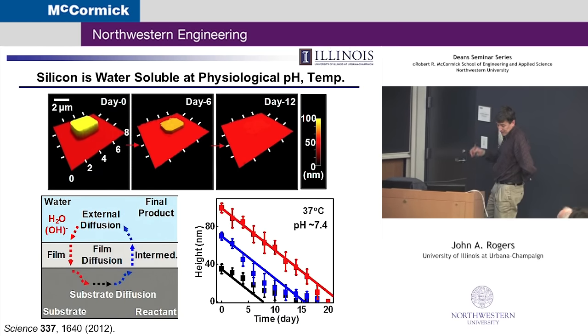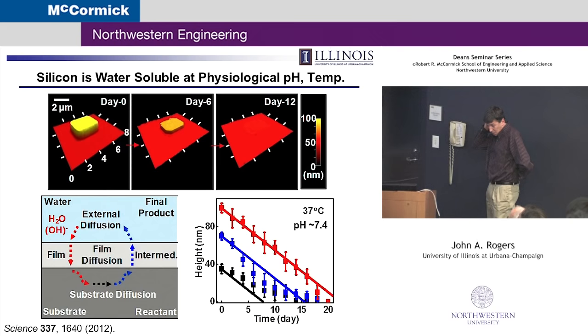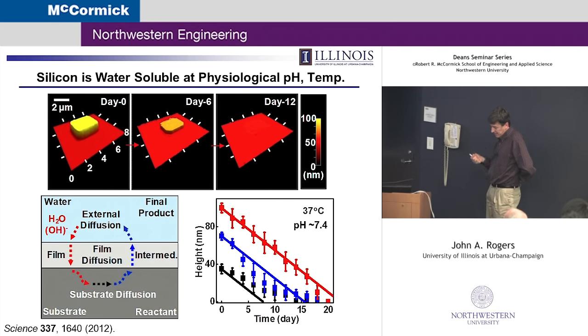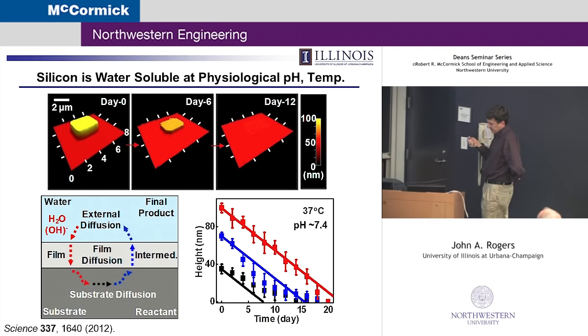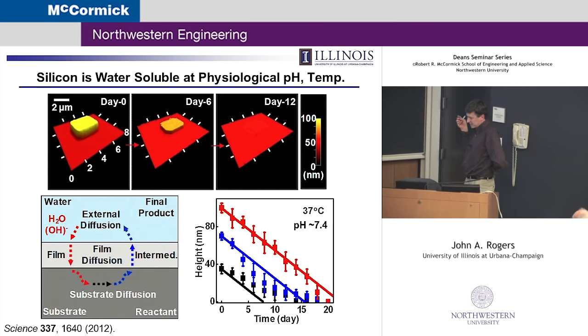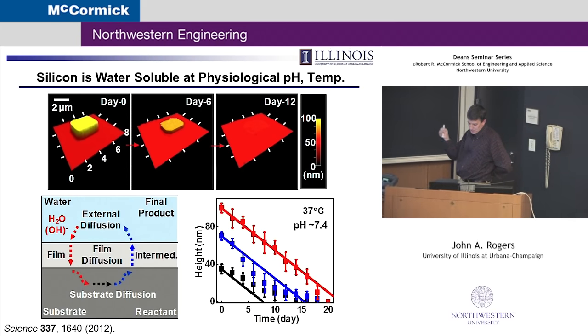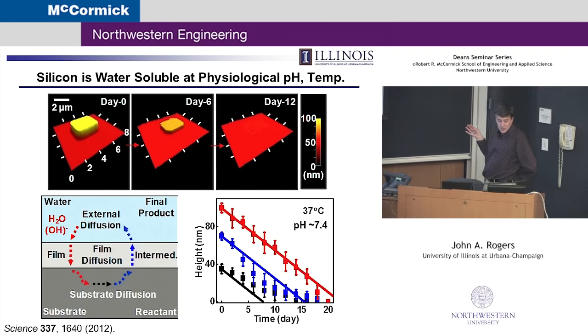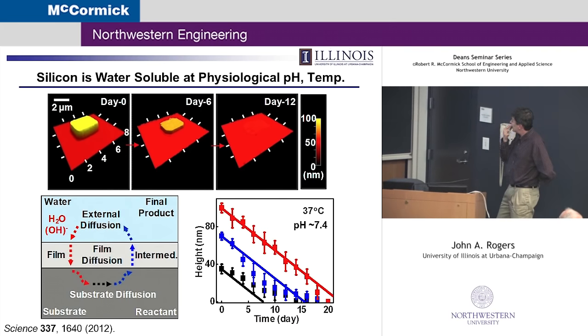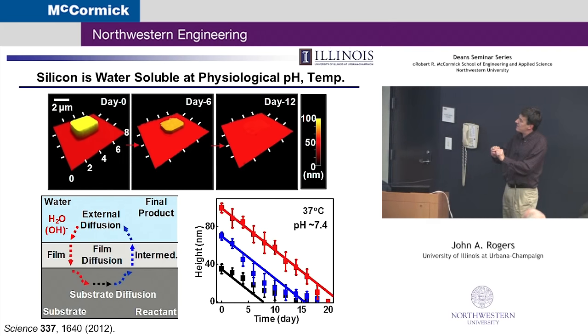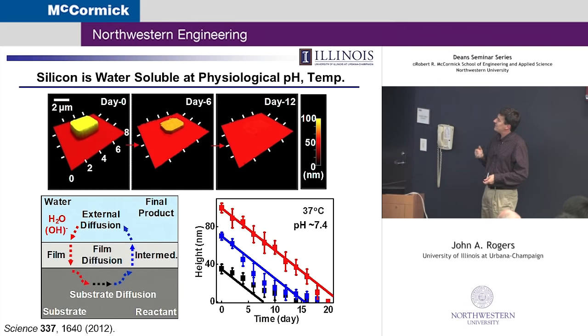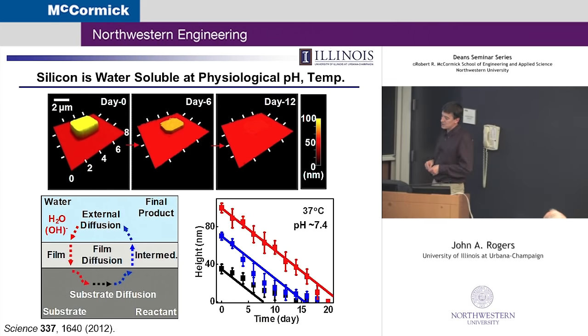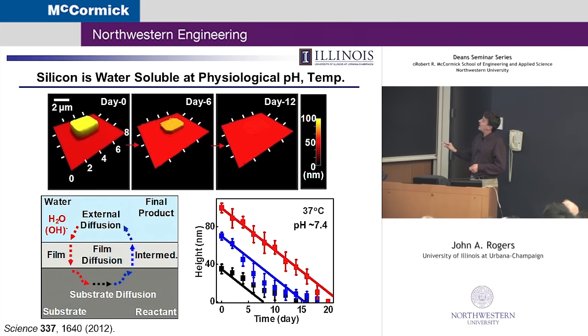So how do you do it? We grappled with this for a while before stumbling on the solution. You think about material selection for electronics, and you add the additional design constraint that it's water soluble, but you might think, there's no way to do that. But it turns out that silicon itself, in these very thin forms, dissolves at physiological pH and temperature values. Because they're so thin, hydrolysis happens at rates that are relevant to the applications you might think about. And that was a lucky coincidence.